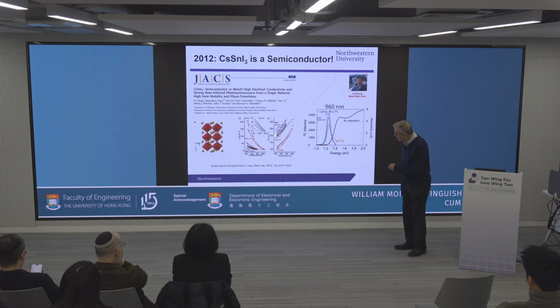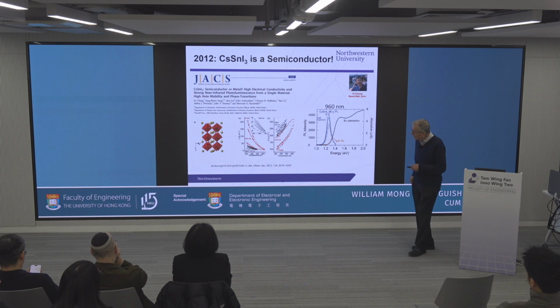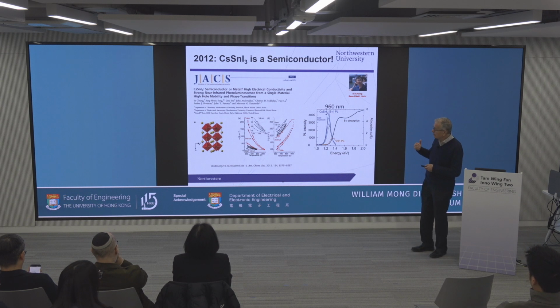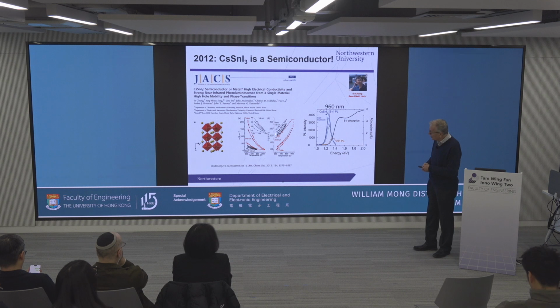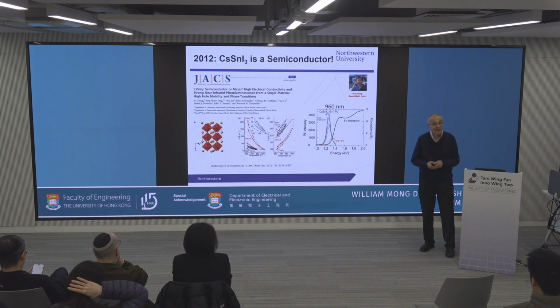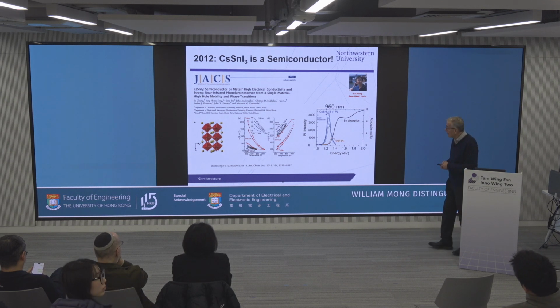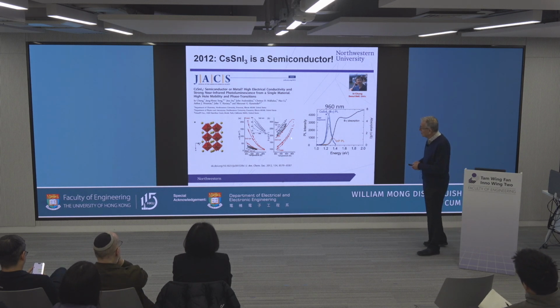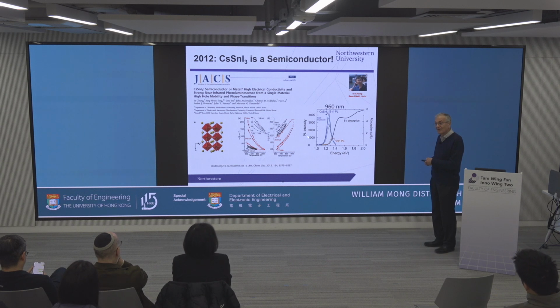Now we also measured the Seebeck coefficient, which is a measure of whether we have N-type or P-type. If it's positive, you have holes. If it's negative, it's electrons. Clearly, this is positive. And the more holes you have, the lower the Seebeck. And the same thing happens here. You have high Seebeck with very few holes, and then you cool and heat in air, and this is what happens. So the air dopes the material. Now that we understood this, we knew we can have it both ways. We can have a conductor if we wanted it. We can have a semiconductor if we wanted it.